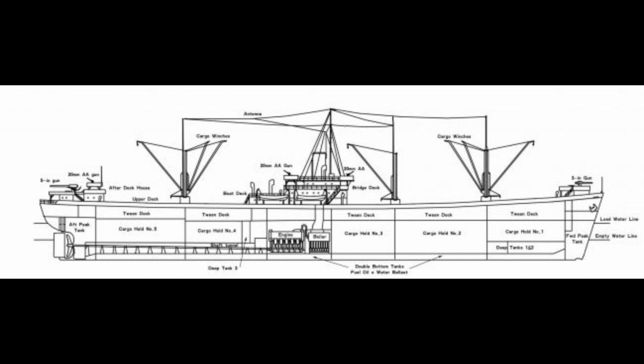200 Liberty ships are lost to enemy action during the war. Torpedoes. Mines. Air attack. Kamikaze strikes. Surface action. The loss rate is approximately 7%, far lower than the 50% loss rate initially feared. The combination of improving convoy tactics, increasing escort strength, and Allied air superiority protects the ships reasonably well.